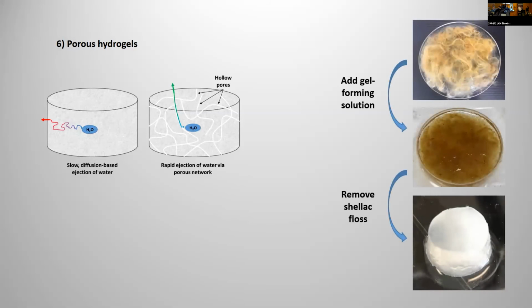So to do this, I had a removable shellac floss template. So all you need is to have a material that is not going to be soluble in water. So shellac is just one example. You can use any other materials that aren't soluble in water. So all you do is cast your hydrogel around this template, cross-link it, and then remove the template. So for this one, it was just removed by soaking in ethanol. But if you can think of other templates that you want to put in there that are dissolved in other ways, whatever you can think of, should be possible.